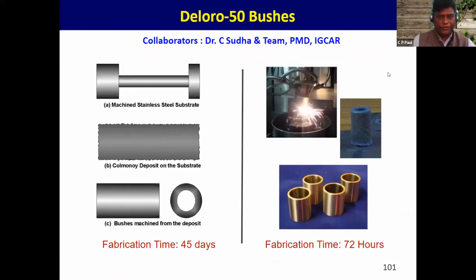One of the beautiful examples is making Deloro 50 bushes. These bushes earlier were made using a conventional method. And why Deloro 50? Because Deloro 50 is one of the materials used in reactors to circumvent the galling problem. What people used to do is take a machined SS rod and deposit Colmonoy or Deloro 50 material or wire using a conventional method. As a result, there was a lot of dilution of the substrate, and people had to go for a lot of machining to give the shape of the bushes. As a result, they used to take 45 days to make such bushes.